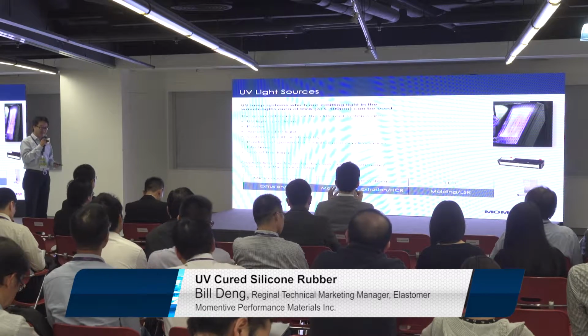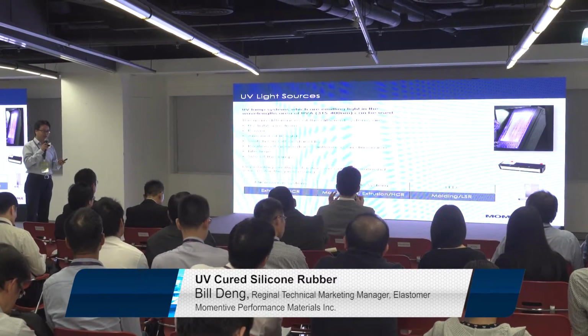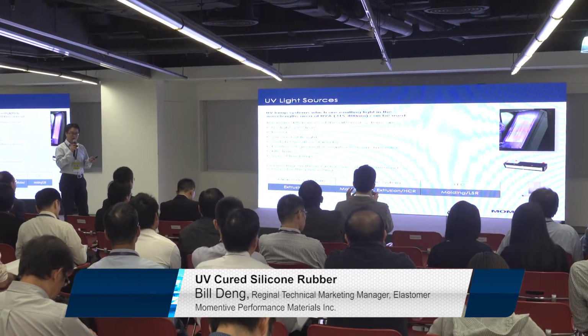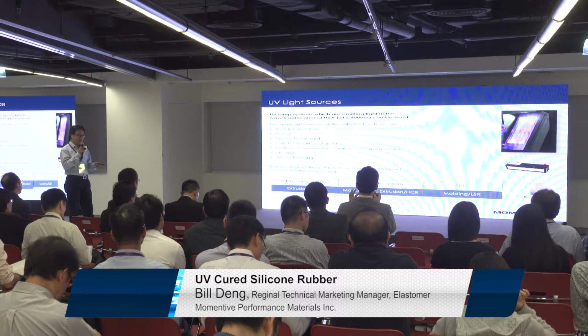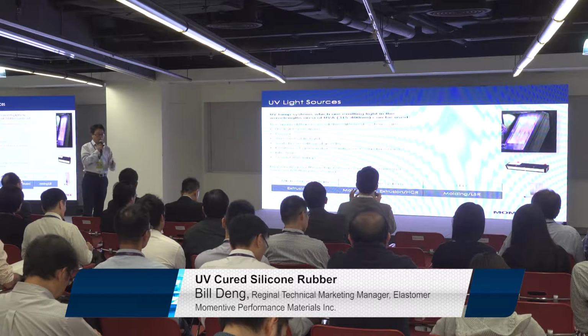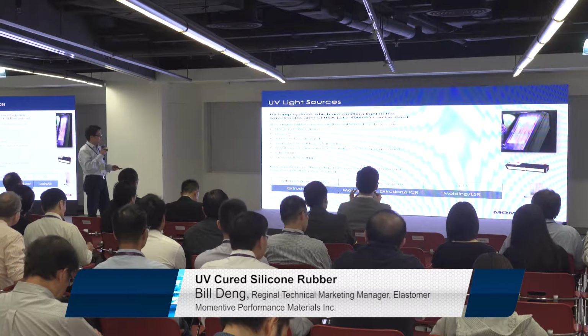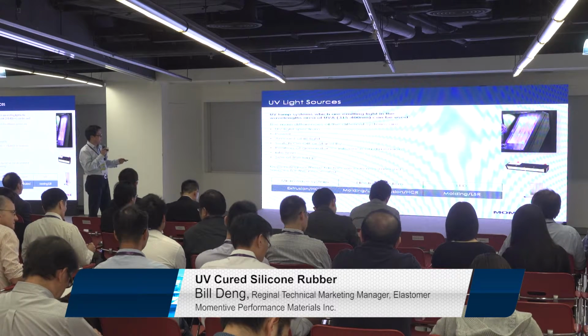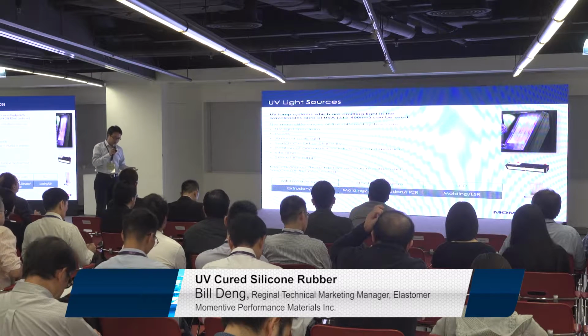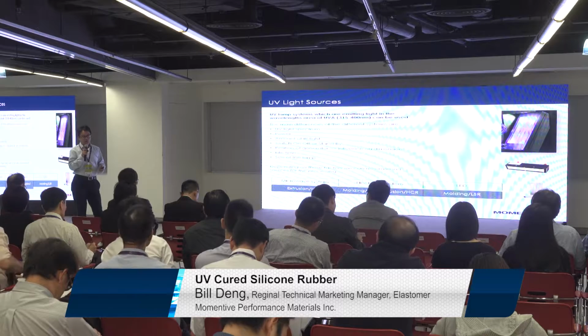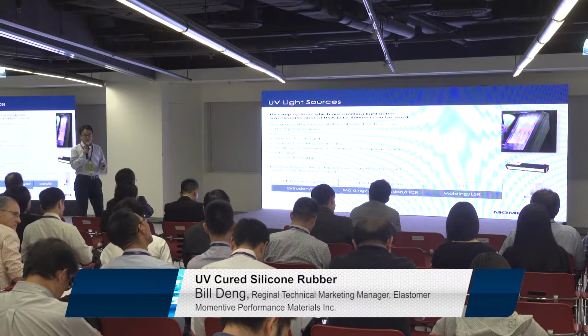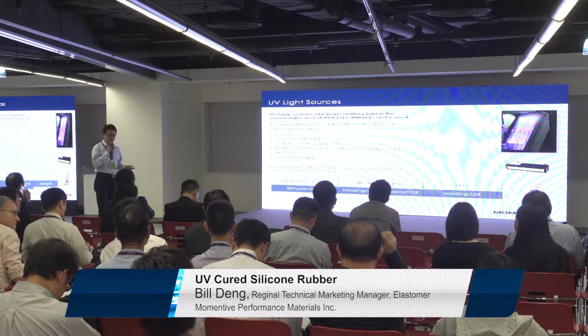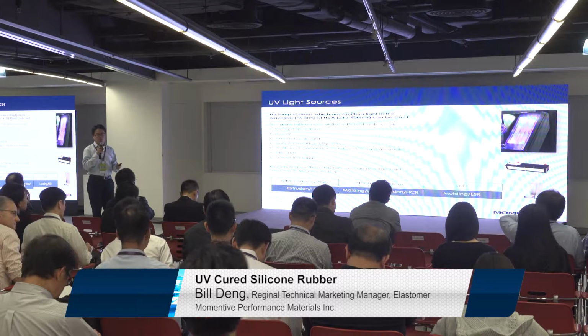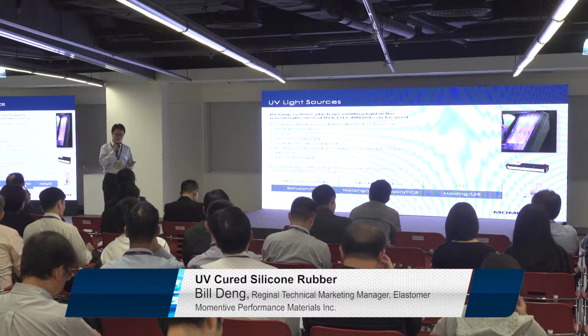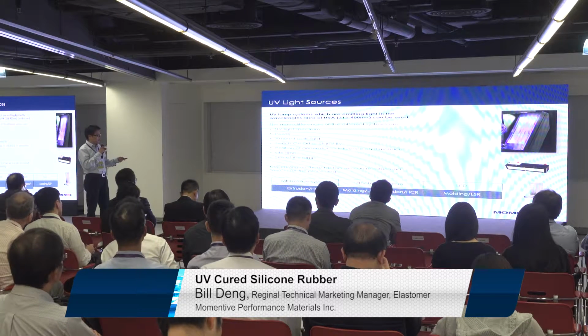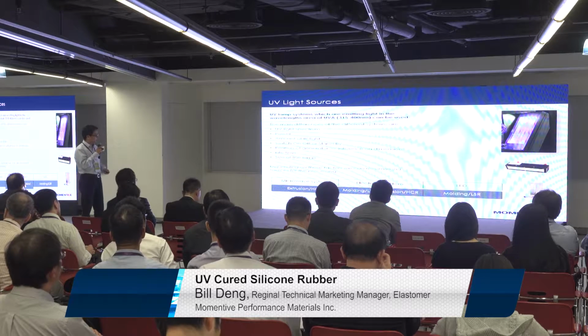But for a very precise small part or a very complicated geometry, it's better to use LED because the LED UV spectrum is much narrower. At the same time, we also need to think that the UV light cannot contain too much IR light, because sometimes when the customer chooses a UV light made by just a regular UV manufacturer, it contains IR inside. But IR will generate heat. In that way, the heat will destroy the transparent mold. That's why we need to remove the IR spectrum from the UV spectrum.